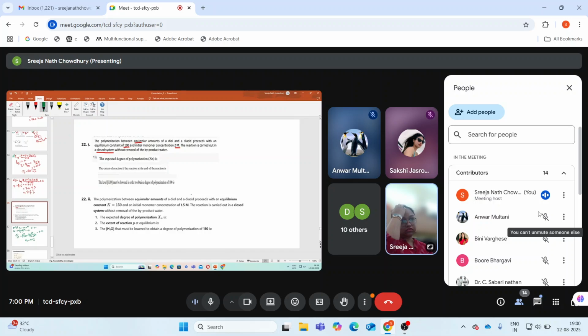So, the rate of initiation, that is Ri, where the rate constant of this dissociation is Kd, is equal to 2f Kd and concentration of I. Why is it 2? By IUPAC convention, here it is given as 2, but 2 is taken because one initiator gives 2 radicals.